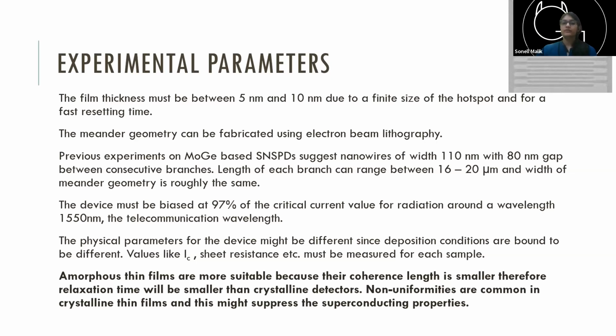But for amorphous thin films, since the coherence length is very small, the electron will much sooner hit some part of the lattice and transfer its energy, which is why they're much faster to cool down. Also, crystalline thin films will have non-uniformities, especially because they're thin films. So you will have sectionalization. You will have what are called crystal boundaries.